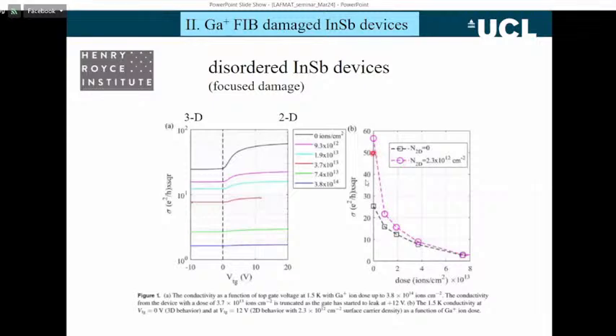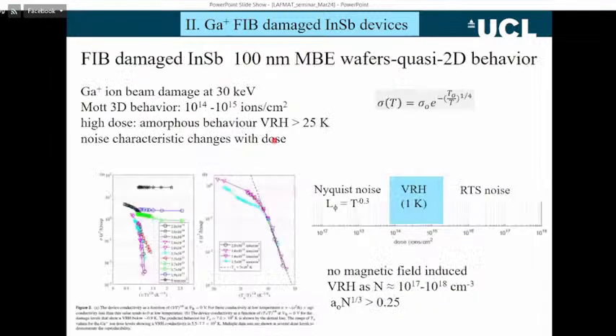And the diagram on the right here shows the device conductance as a function of ion beam damage. As we put more damage in, the conductance drops down. So the purple color is when we've got the surface region, the 2D surface, and then the black is just how the bulk changes. We've got no 2D region, it's just the bulk. Okay. So a little bit more information on these devices. They were 100 nanometers thick, so they started at 100 nanometers thick. They're grown on gallium arsenide. They kind of have a quasi 2D behavior. And we use gallium ion beam patterning at 30 kilovolts.